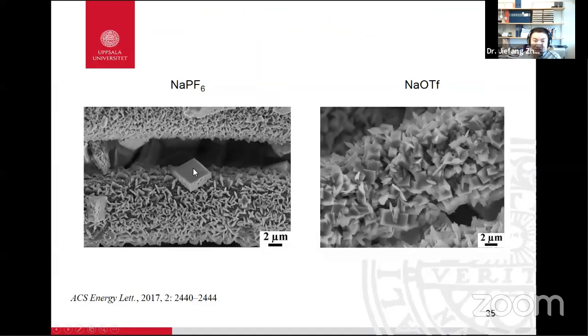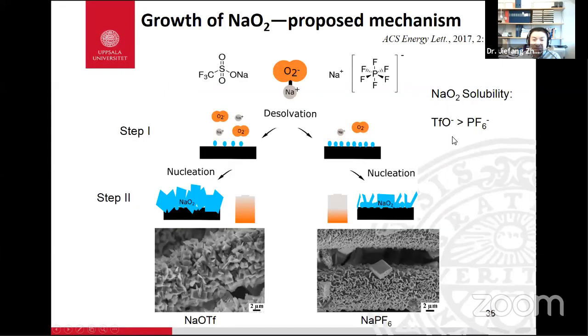The reason for that is, for NaPF6, we could see several big blocks, big size of sodium superoxide, but for NaOTF, it has an even size distribution. So we give the purpose for the growth of sodium superoxide: because NaOTF has higher solubility of sodium superoxide, it can form in the solution until it is saturated, so it can start to slowly precipitate.